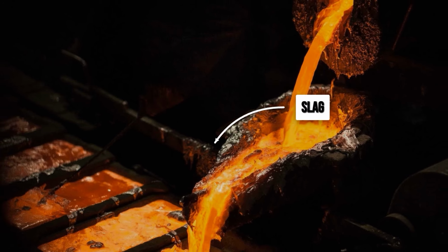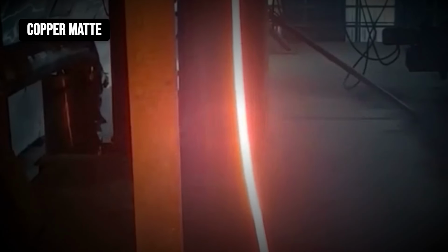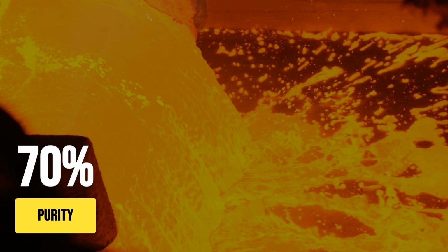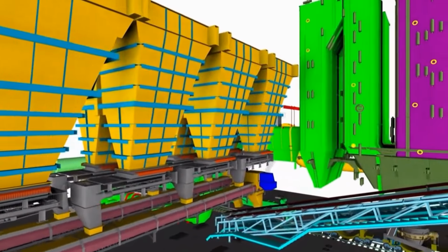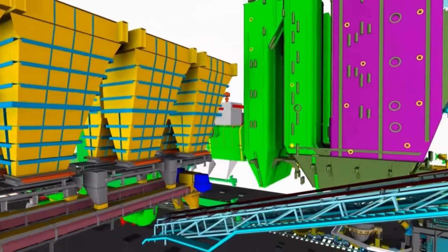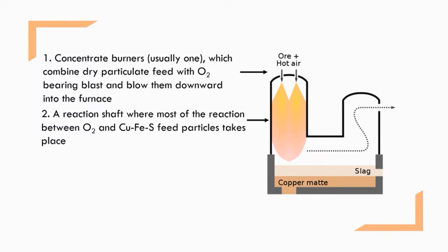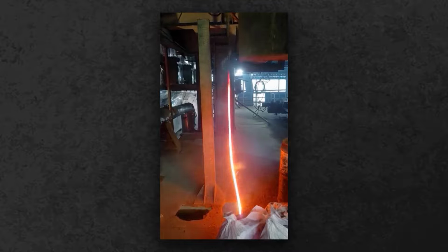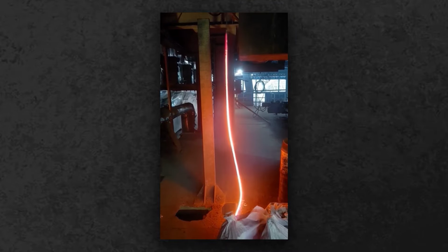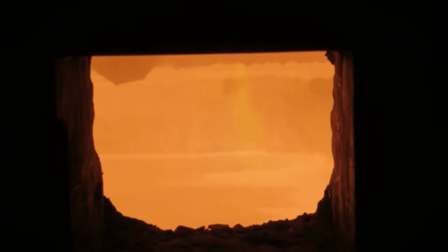Slag, filled with unwanted minerals, floats on top. Below, a dense layer forms. Copper matte, glowing orange, holding 60 to 70% pure copper. The chief metallurgist watches the separation through heat-resistant glass, scanning for subtle color shifts that signal the right chemistry. Each tap of the furnace drains out matte at just the right moment, a stream of liquid metal flowing into waiting ladles.